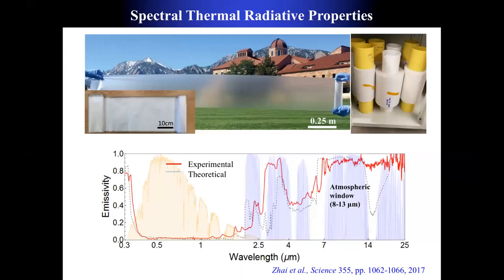Now, if we back it up with a silver or metallic coating, we end up with something really bright, with a whitish color on the left part. And that's what we have in terms of the metamaterial. Now, if we check the thermal radiative properties, on the left it reflects sunlight almost perfectly, 96% of sunlight being reflected. And in the atmospheric window, 8 to 13 micron, we have almost perfect emission. In this figure, we also show the theoretical calculation and the experimental results. They compare reasonably well, especially in the wavelength region we are interested in.